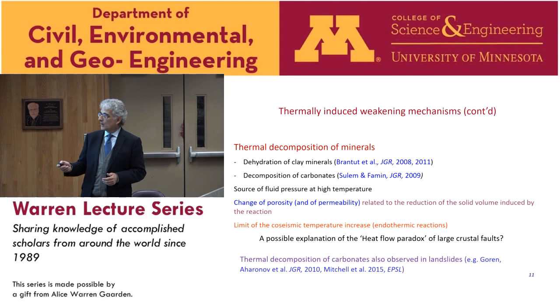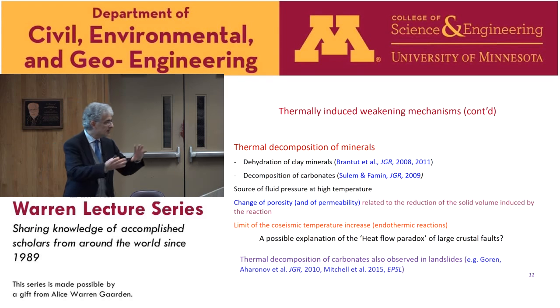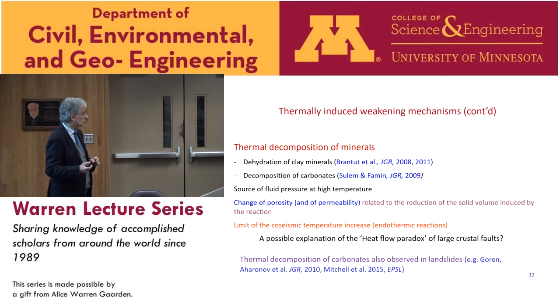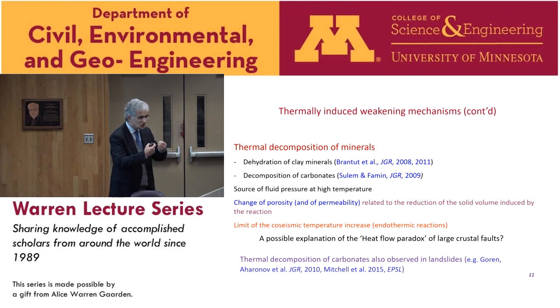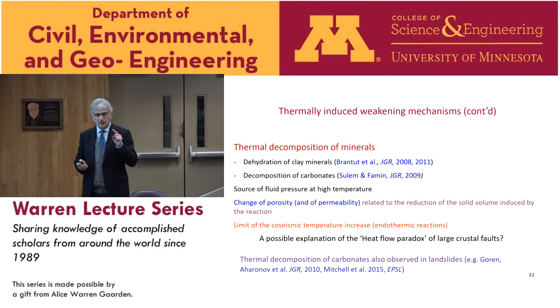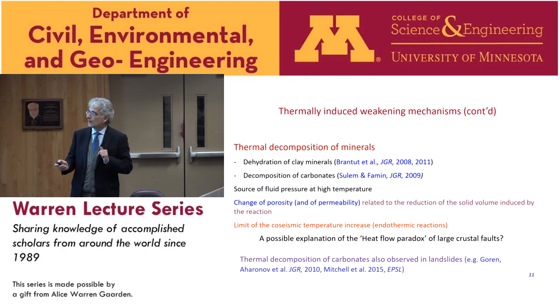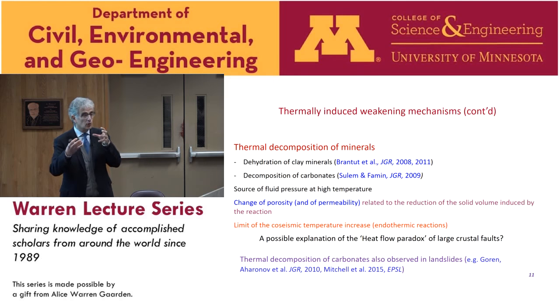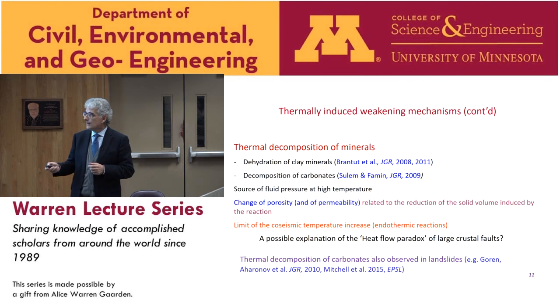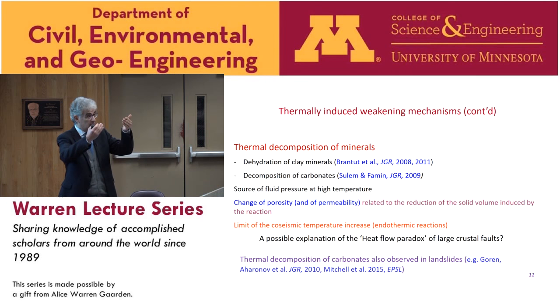Also, thermal decomposition induces a reduction of the solid volume. So in competition with this increase of the pore pressure, we can have an increase of porosity and of permeability that will be in competition with the pressurization. From the energetical point of view, these chemical reactions are endothermic, which means that part of the frictional work is actually used in the reaction. And the consequence of that is that it will limit the increase of temperature.